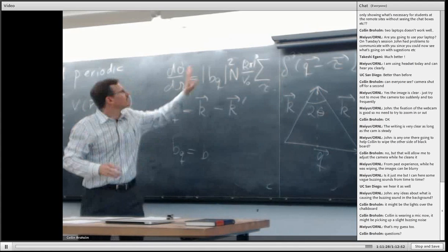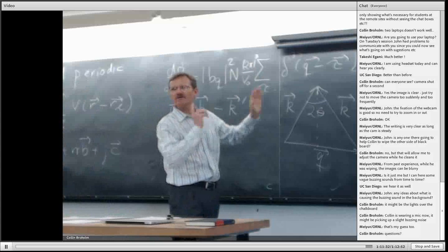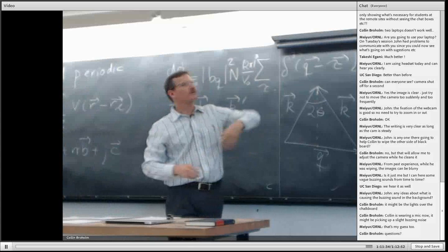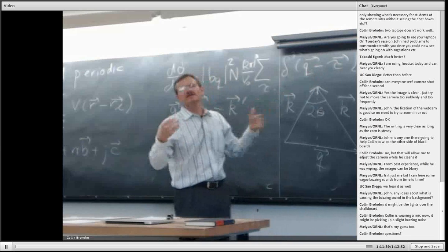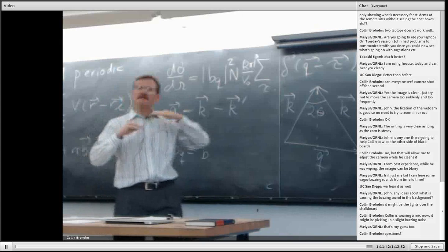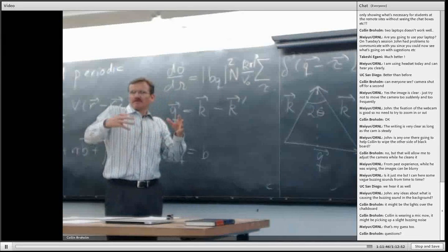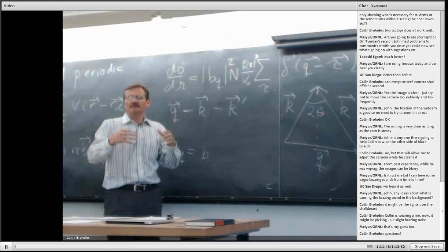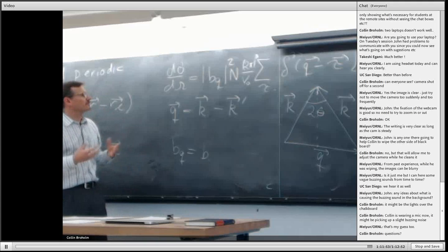So our formulas here would produce exactly the same intensity for all of the delta functions going all the way out to extremely large values of momentum transfer. But what I'm telling you is that as a result of zero-point motion and thermal motion, we would expect that the higher Q peaks will actually be attenuated because the potential is somewhat spread out in real space. So that's something that I'm sure Takeshi will describe to you.